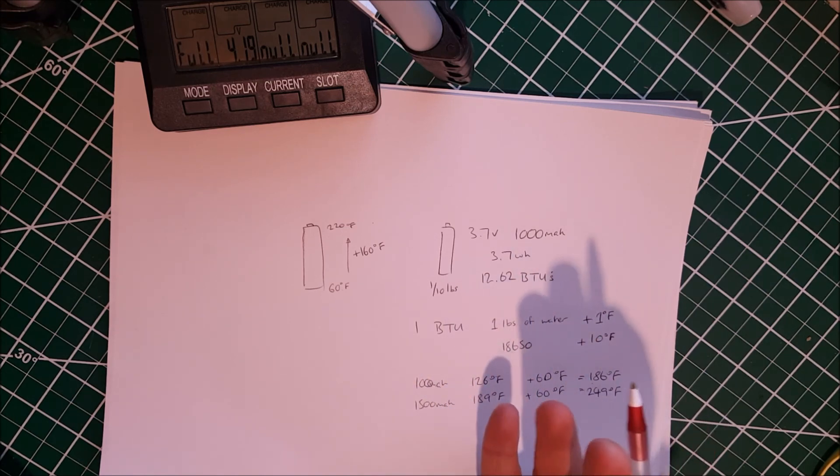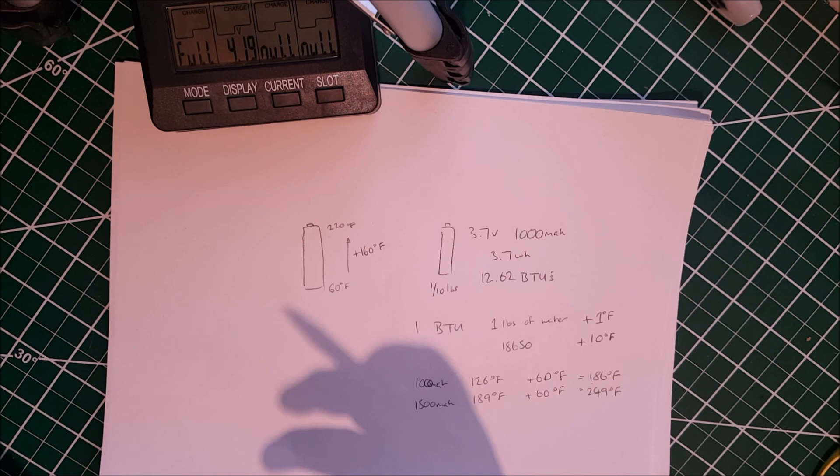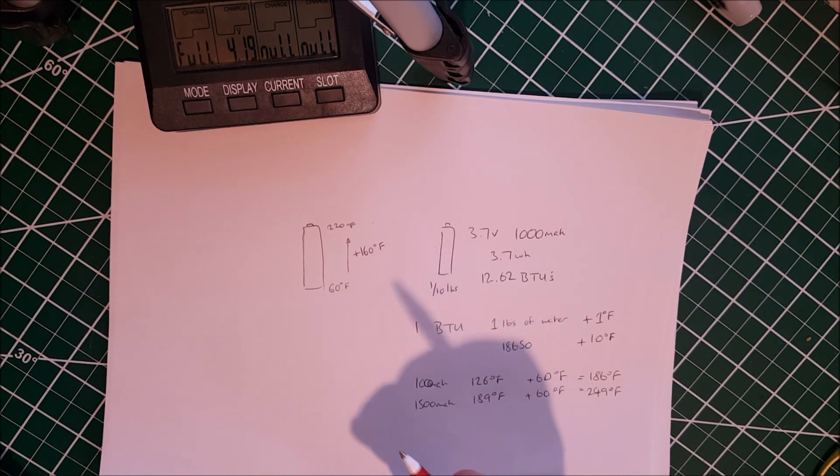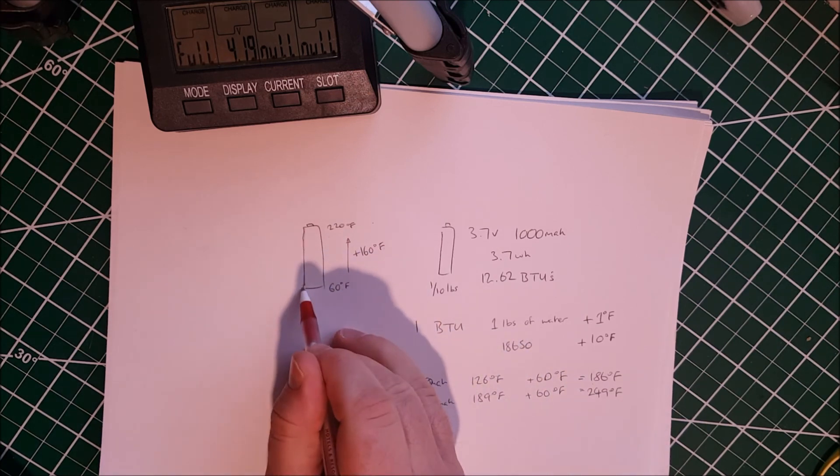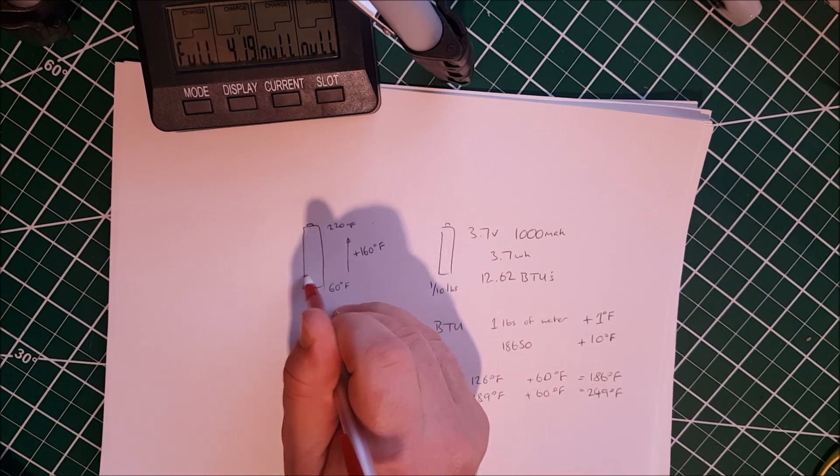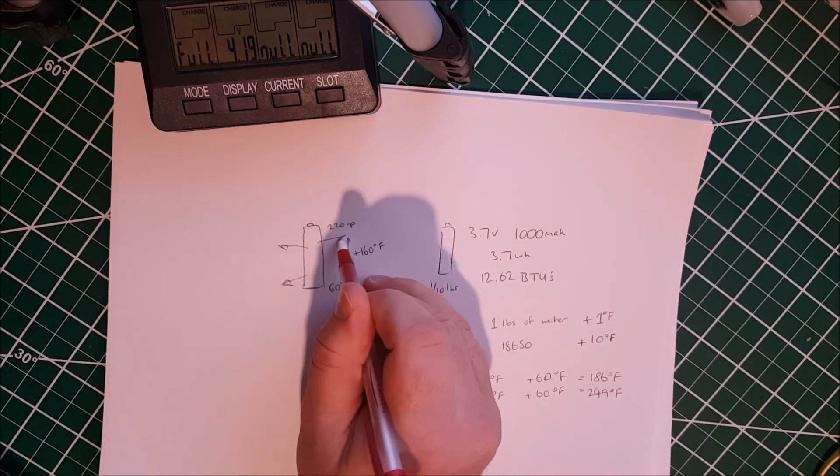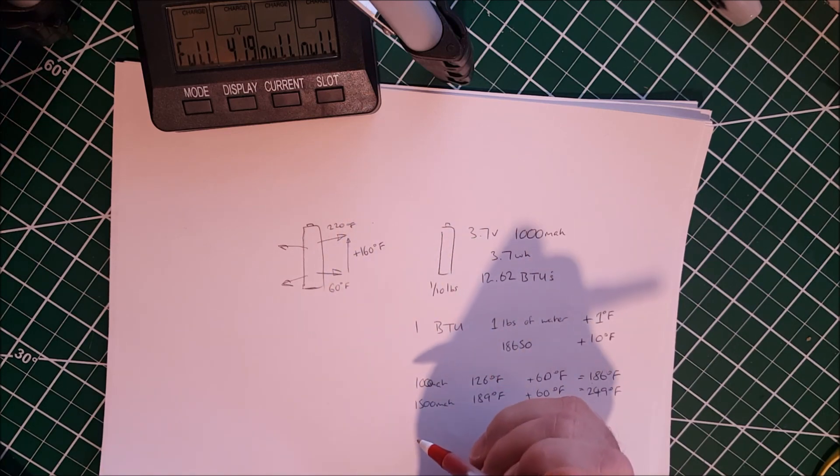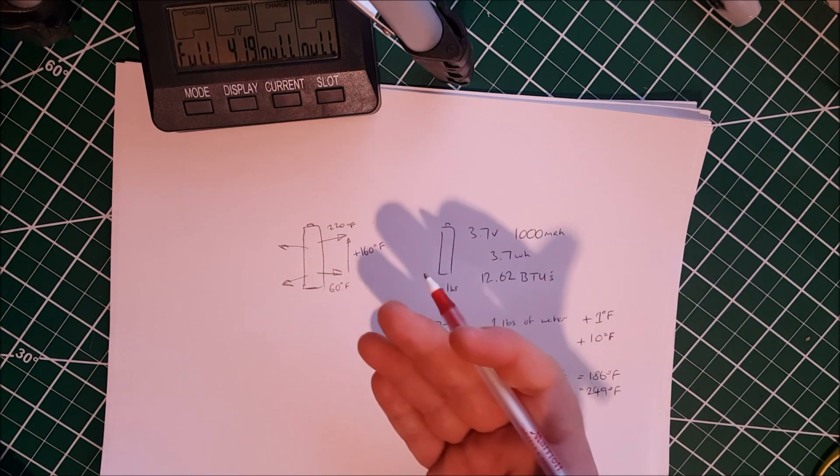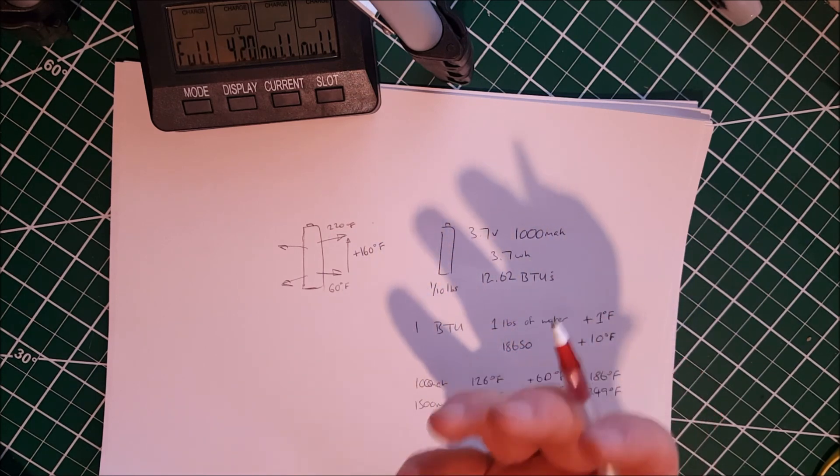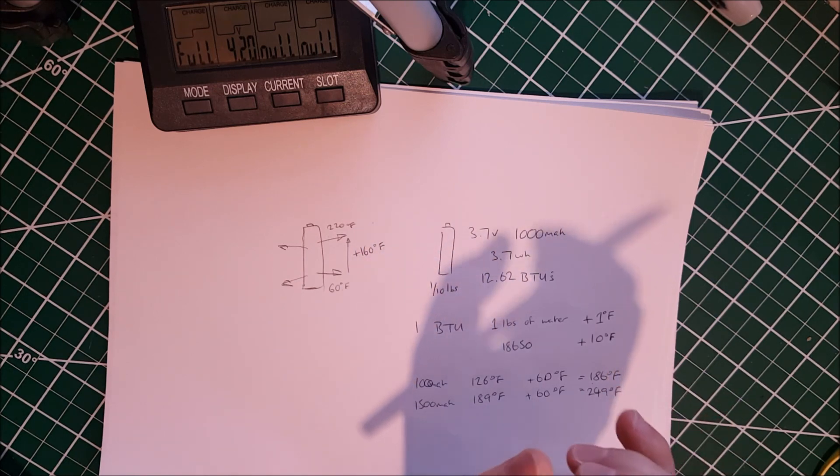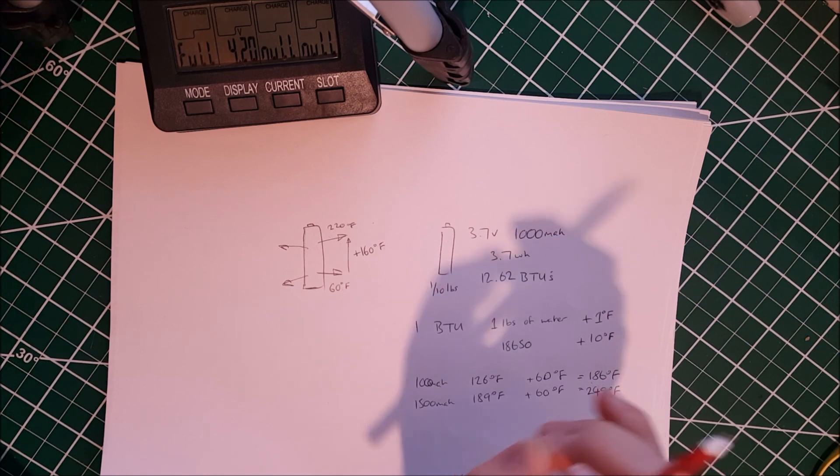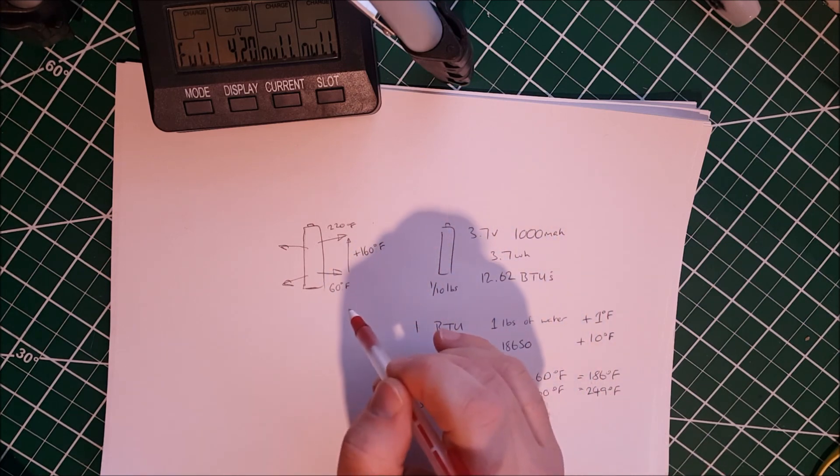So how do you stop it? From what I can tell, the trick, besides the design of the cell being able to handle a thermal runaway, the trick is to really dissipate the heat as quickly as you can to avoid hitting that critical temperature. So we're down here and we're dissipating heat, and if we start to increase this temperature, we need to get rid of the heat somehow. And how do we cool these cells? In a lot of power walls that I've seen, they're in a grid formation, and the heat can be transferred via the surrounding air and also to other cells via the mechanical connection.